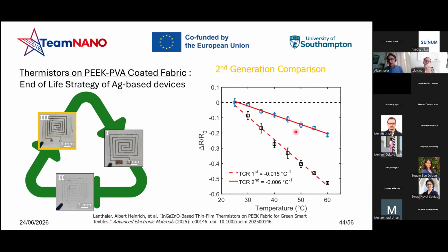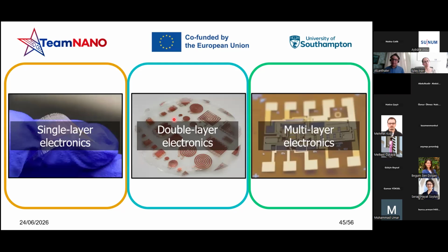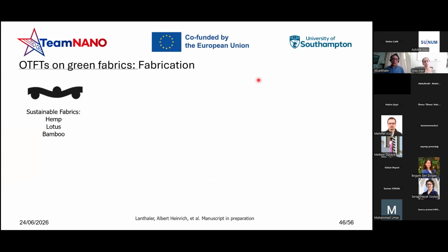As you can see here, making a comparison between the two calibrations of the first generation and the second generation, there's a decay in performance. We believe it is mainly due to, again, some residual stress during the recyclability process on the fabric itself. Finally, coming to the multi-layer electronics, the idea is to fabricate organic thin film transistors on green fabric.